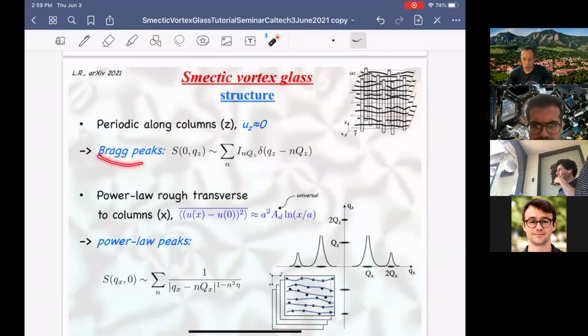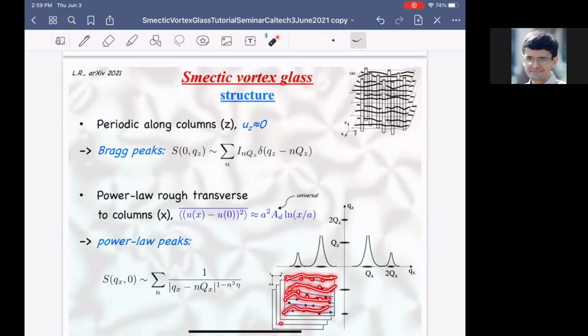And one can probe that order by calculating the structure function. So scattering along the q_z, along the columns, you get true Bragg peaks. Okay, because at low temperatures it's like a one-dimensional crystal in the sense that this is periodic. On the other hand, if you look transversely to columns, then the vortices just see this point disorder coming out of the page, and they're randomly pinned like this.